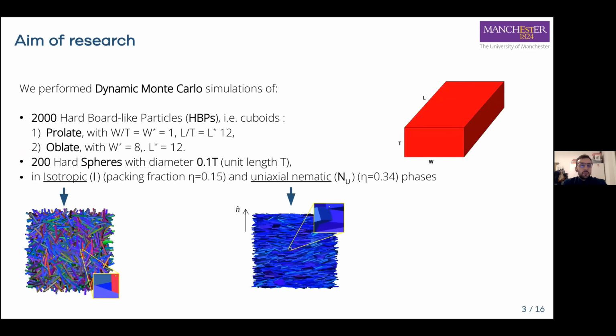For this reason, we performed dynamic Monte Carlo simulations of hard board-like particles, so cuboidal particles with different shapes, prolate and oblate. We use the thickness T of the cuboids as the unit length of our system. And we perform simulations of cuboids with relative length equal to 12 and relative width equal to 8 for oblate cuboids and 1 for prolate cuboids.